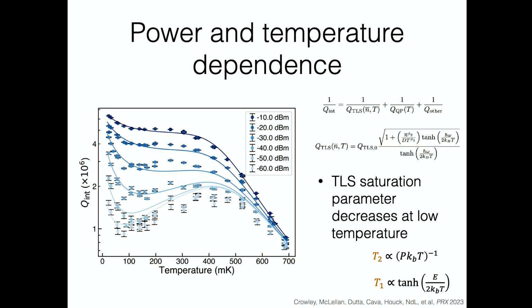So this is two-level systems, which can thermally saturate and also saturate with power. These are quasi-particle losses that turn on when you break Cooper pairs in the superconductor, and then you have these free electrons around that give you resistive loss. And then I have something that sets a ceiling. Okay, so we don't have to talk about the details of this model, but the real takeaway that I want you to have is this is a very beautiful fit to the data. By just writing down something with seven free parameters, I can really capture every single bit of curvature for these things right away.